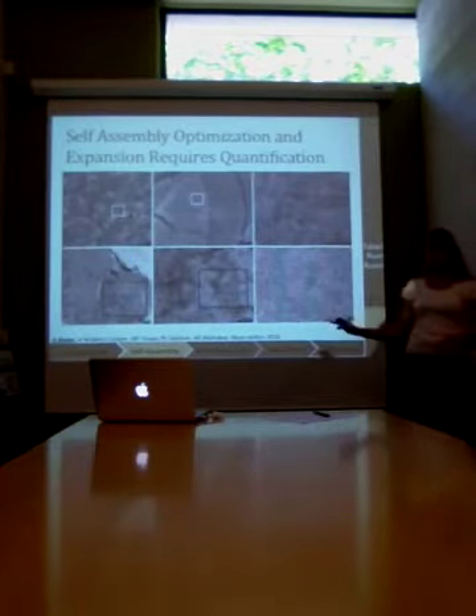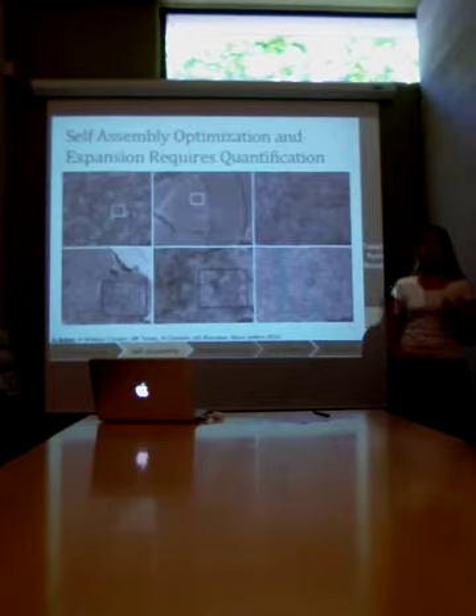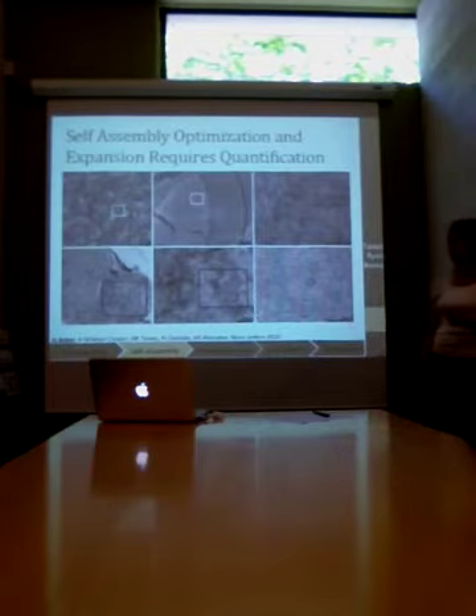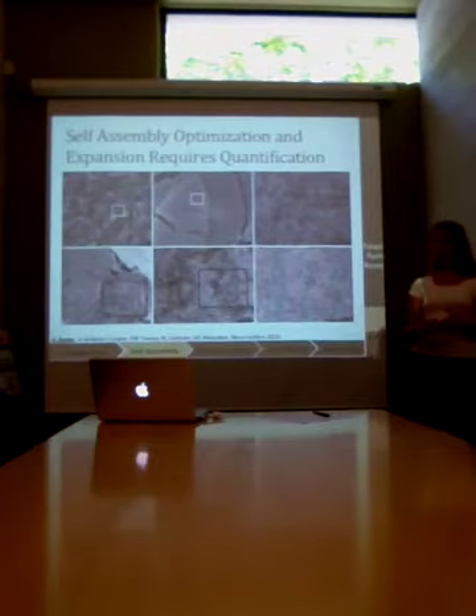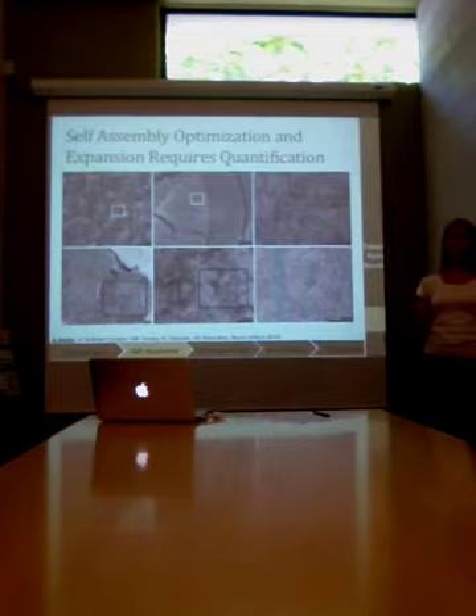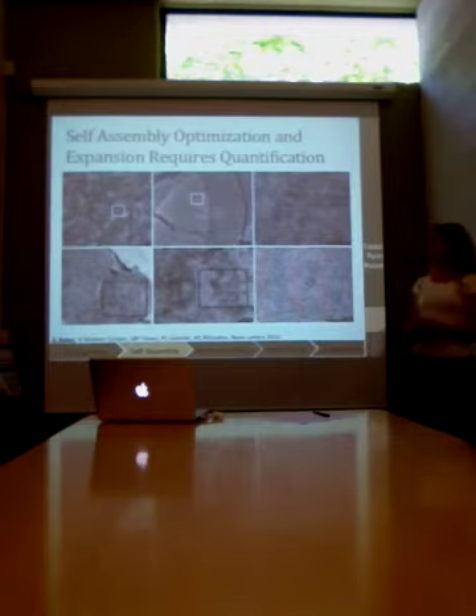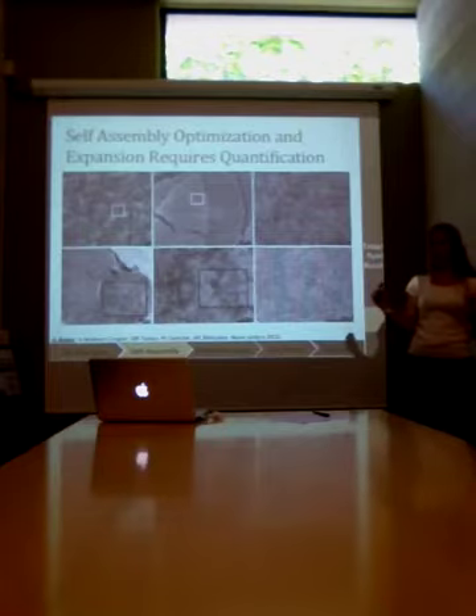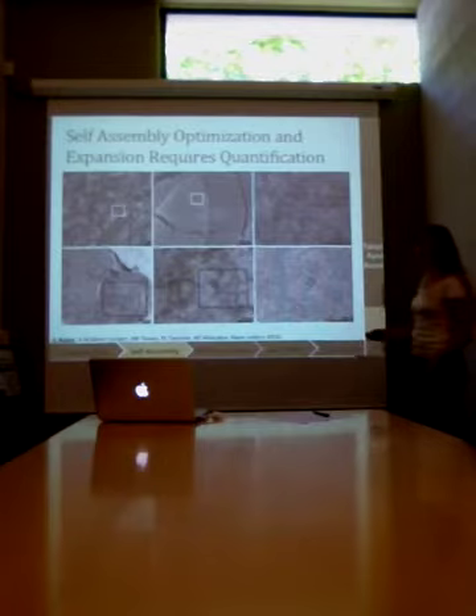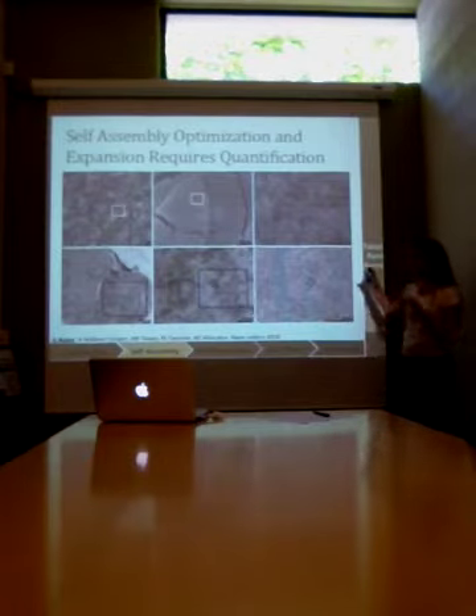And at the point when we started doing this research, there were 3 groups that had demonstrated nanorod alignment previously: Dmitri Talapin, Kevin Ryan, and Tom Russell. But they had all demonstrated alignment on a very small scale of hundreds or thousands of nanorods, less than a square micron. And our goal had been to scale this to a square centimeter, and we weren't using the same techniques that they were using. So this is 8 orders of magnitude, and the first thing we noticed as we began to assemble these rods